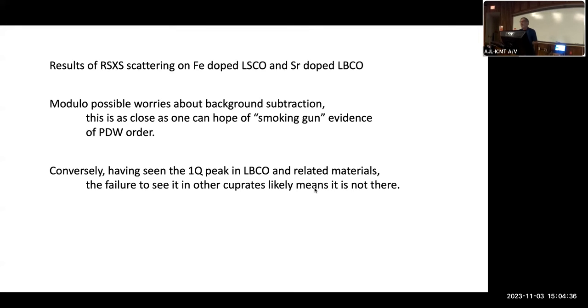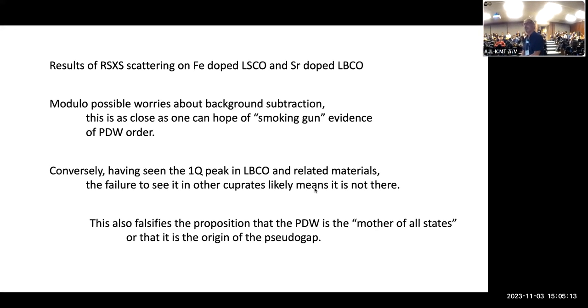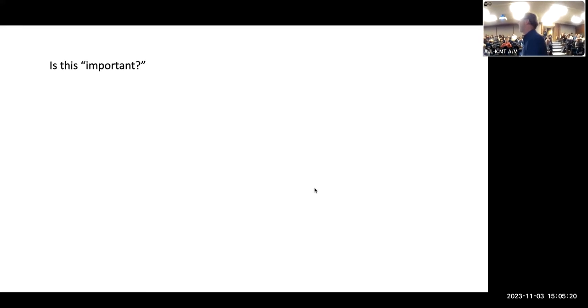And now let me conclude. So I wanted you to be aware of the background subtraction. It is standard, but it's a big background subtraction. Modulo that worry, this is as close as one can find to a smoking gun of this pair density wave. And conversely, having seen this 1Q peak in the material where layer decoupling made us think there should be pair density wave, the absence of this 1Q peak in other cuprates should be taken as serious negative evidence. So this falsifies the mother of all states proposition. Okay, so I'll stop.